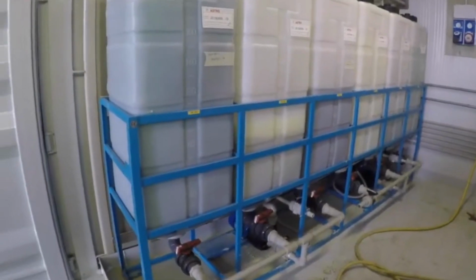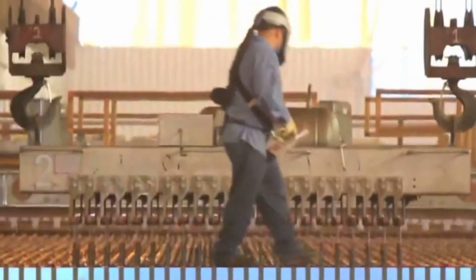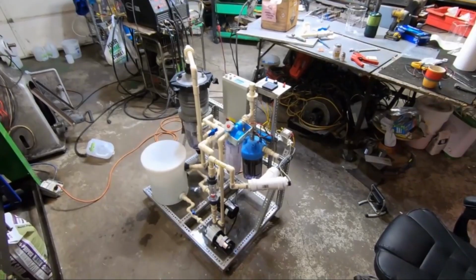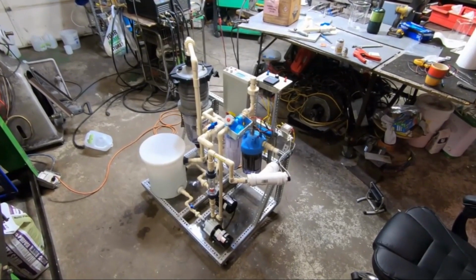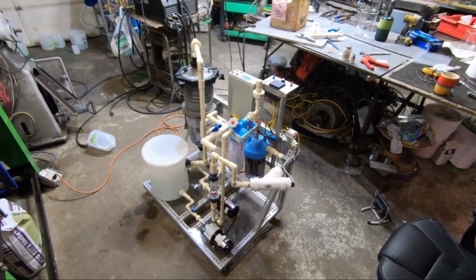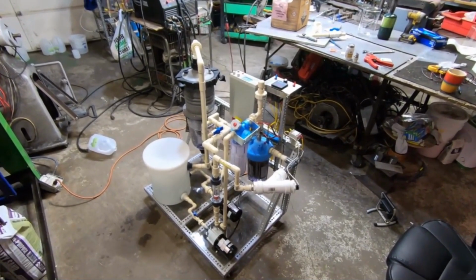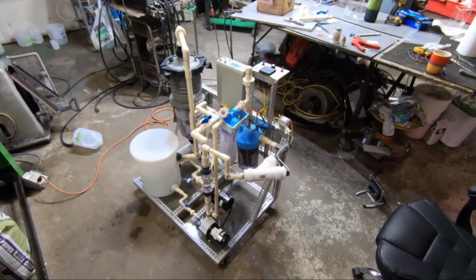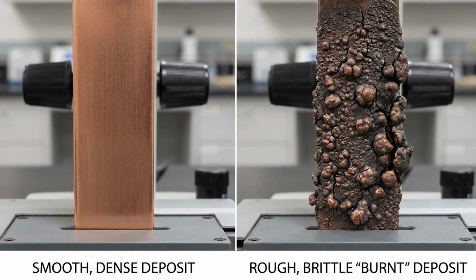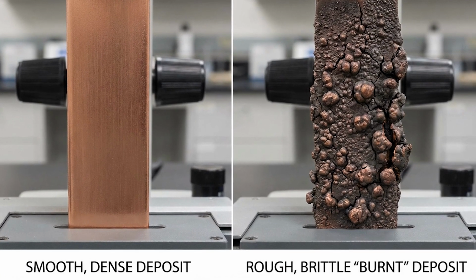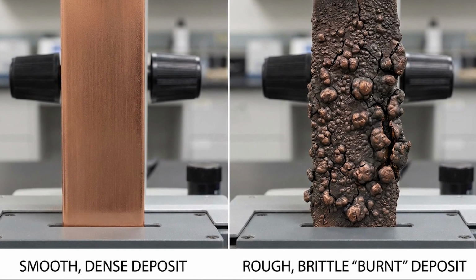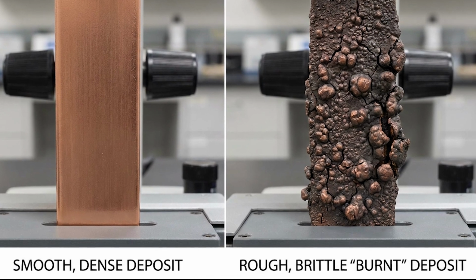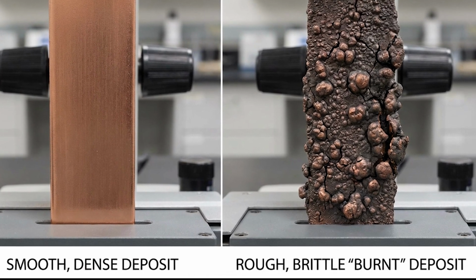So real plants lock chemistry into rails: pH probes, ORP probes, dosing pumps, temperature control, agitation to eliminate dead zones. Controllers correct pH and redox every few seconds, faster than operators can react. If ORP overshoots, impurities follow the copper. And later, instead of smooth copper sheets, you plate rough, brittle, burnt deposits that have to be scrapped.